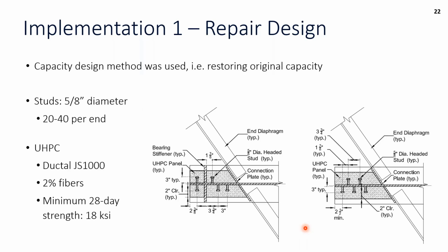So here's a couple of pictures from the repair design. The designer went with a 5/8 diameter stud, and depending on the condition, we had between 20 and 40 studs required per end. There's a few different design methods that can be used. For example, if you look at different suggestions in our guidelines, there's one where the studs are only really responsible for carrying the live load of the bridge, and others where we want to make sure it's really comprehensively designed, and our goal was to restore the original capacity.